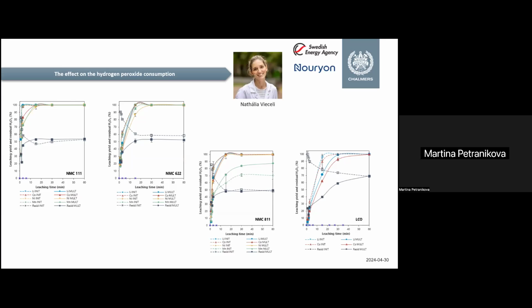So it's a very clean chemical, but it's quite expensive, and its consumption should be optimized. So we did the research on the optimization and on defining the consumption, and we could see that in most cases it didn't matter how we were dosing, whether in the beginning all the volume needed for the reaction, or throughout the experiment. At the end, the consumption was very similar.